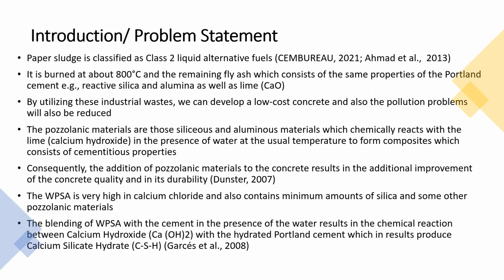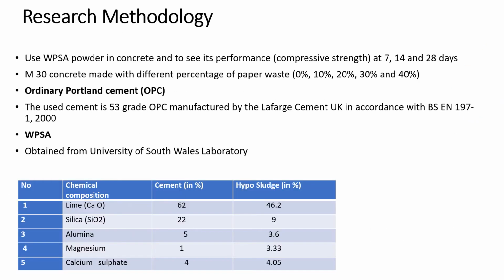The reason for that is that the waste paper sludge ash is very high in calcium and also contains a minimum amount of silica. So the blending of this ash with the cement in the presence of water results in a chemical reaction between calcium hydroxide and the hydrated Portland cement, which in turn produces calcium silicate hydrate. So we have used that ash powder in concrete to see its performance.